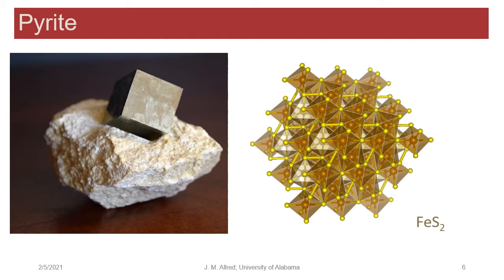I like to show pyrite because everyone loves pyrite mineral crystals. There's a naturally occurring pyrite crystal. And it reminds us to think carefully about chemistry and electron counting, because we know the iron doesn't like to be 4+, but sulfur likes to be 2-, unless the sulfur makes a bond with itself. So you get dumbbells, and those S2 dimers each have a charge of 2-. So it's -1 per sulfur, and so the iron could end up being 2+. And then we can be comfortable with the charges.